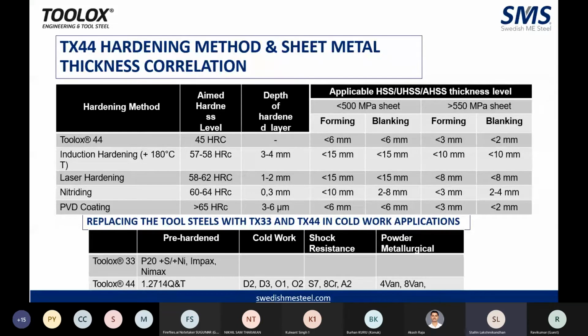For example, if you're using a sheet of less than 500 MPa and want to do forming of less than 6 mm, then Toolox 44 should be good enough. But if the sheet strength is more than 550 MPa and the thickness is less than 3 mm, then you need to be sure about Toolox 44 and other processes. So depending upon where exactly your application stands, this will give you an idea of where to use the material.